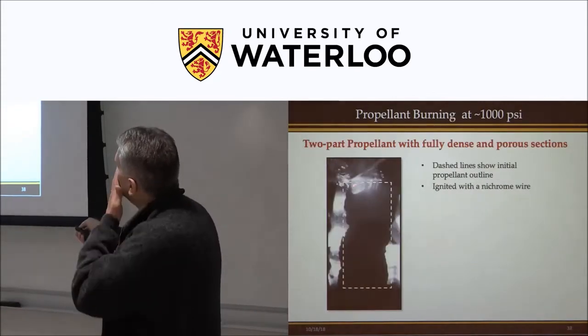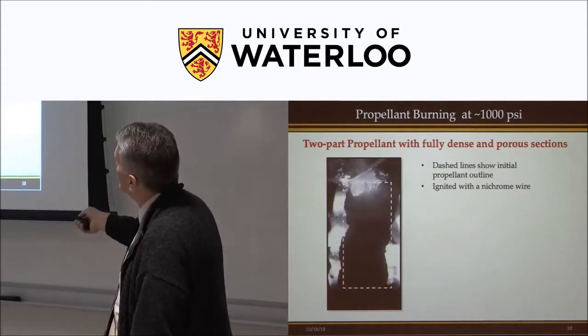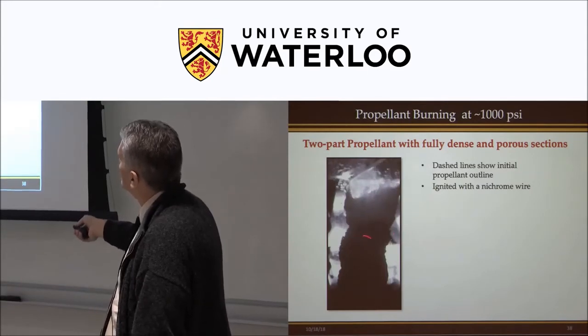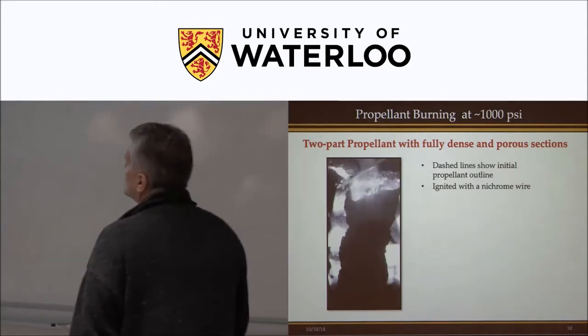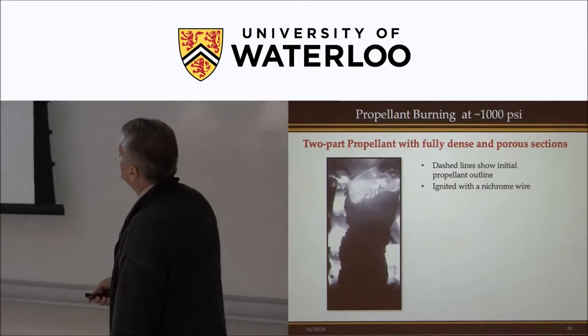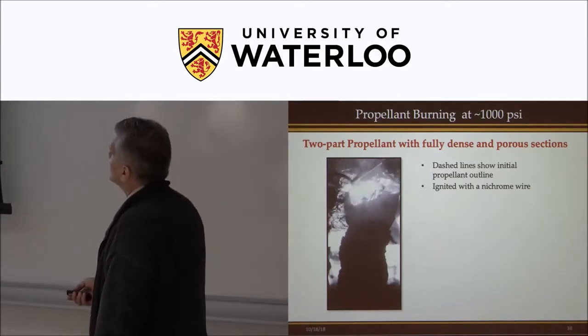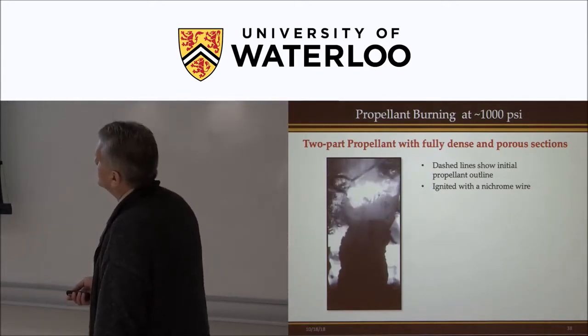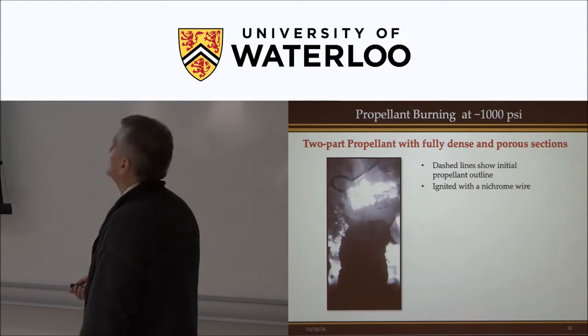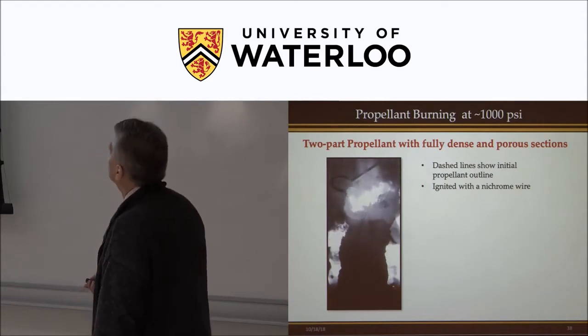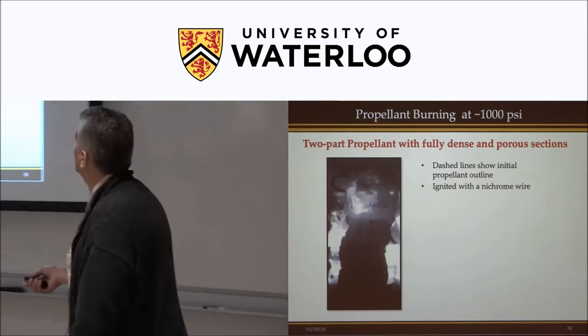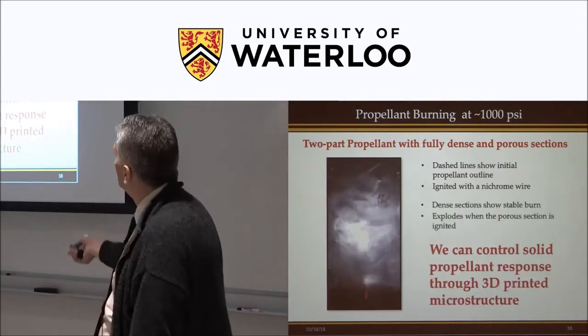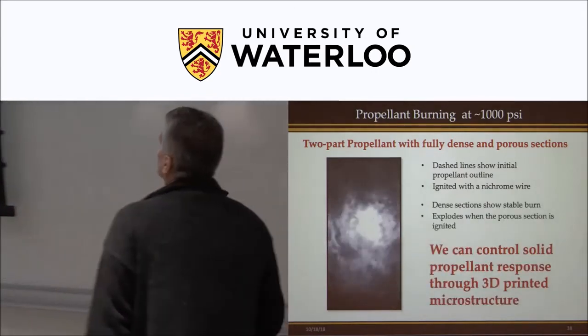So in this case, we have a fully dense case, so this is burning like a normal propellant. It'll get down to this region, and we've intentionally printed some voids into that sample. And there it goes, almost, once it gets down there. There, so it shoots down through the propellant and basically explodes it.